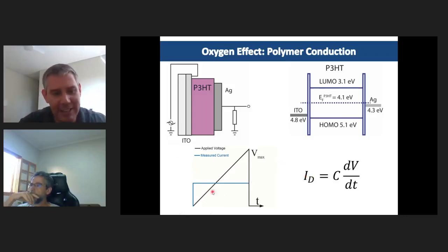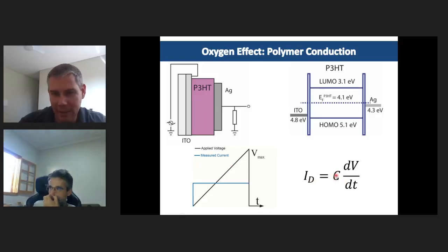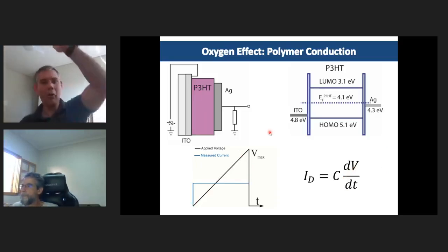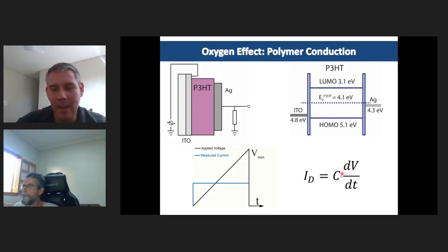So there is a technique that circumvents this phenomenon, and it's basically applying a linearly increasing voltage across the sample through the electrodes. By doing so, we know that the displacement current is the capacitance of the device times the derivative of voltage in time. If you differentiate a linearly increasing voltage, this portion becomes a constant, which is the rate of growth of the voltage. And because capacitance is a constant as well, the displacement current becomes just a constant current, which is illustrated by this blue box of currents. So you apply a linear increase in voltage, and then you measure this constant current.